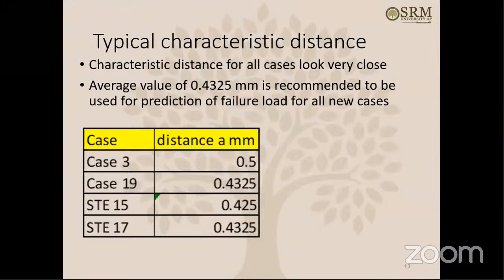So the characteristic distance that I talked about: we studied the baseline coupon, the case 3 coupon, the case 19, and ST15 and ST17. These are just the different designs that we were working on. For all these 4 designs, we compared with the baseline coupon, and we used the experimental results and also the analysis results and found out this characteristic distance. And the characteristic distance looks like 0.4325 is the kind of average distance that can be used for prediction of failure load for all the new cases.